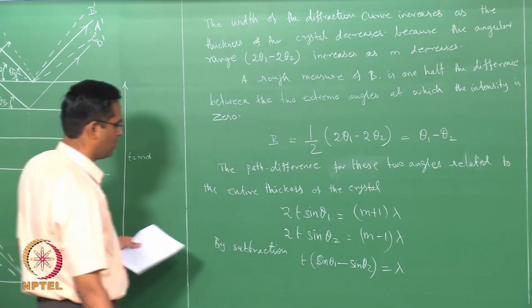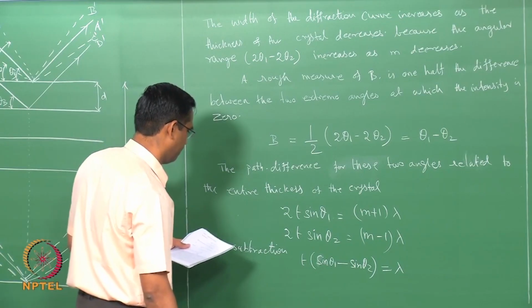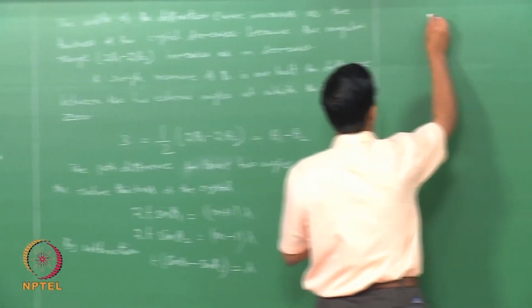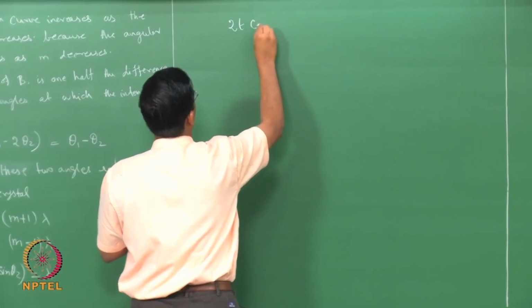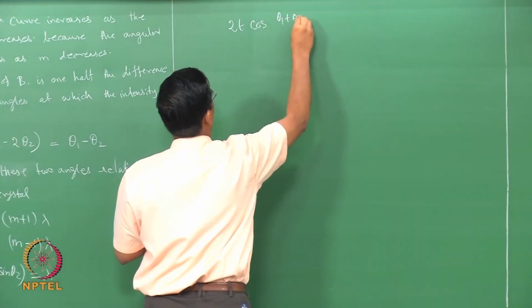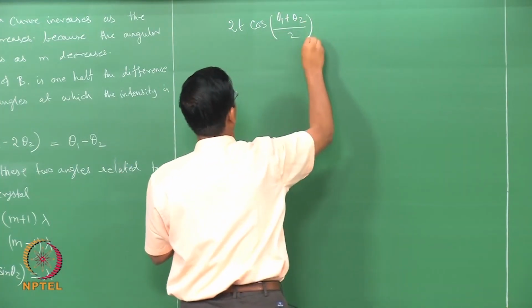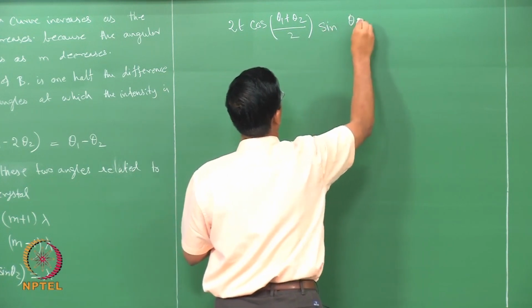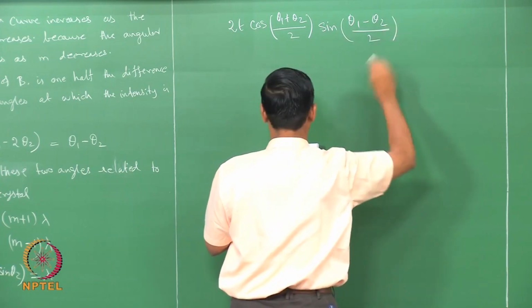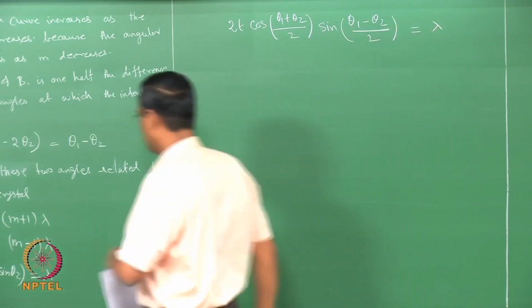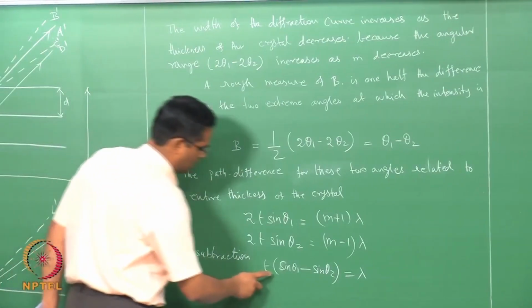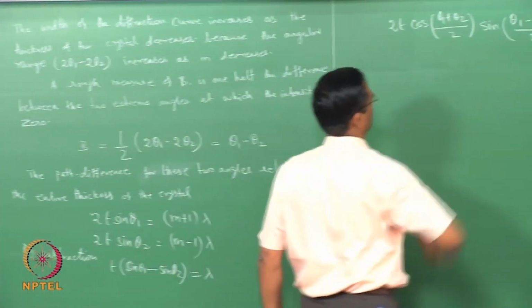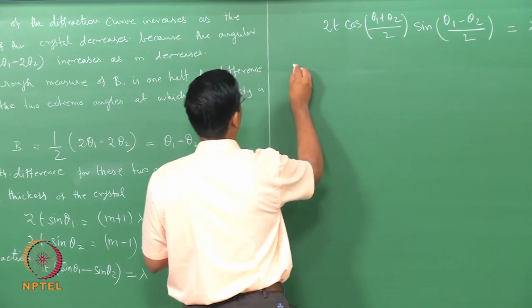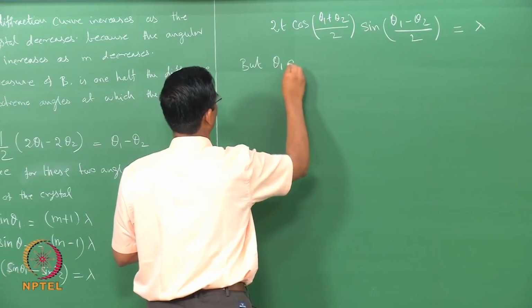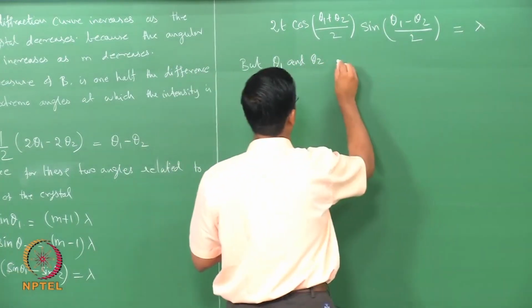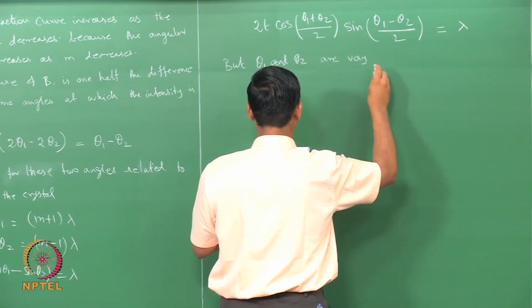So, we can use some trigonometric relations to replace this. We can write 2t cos of (theta 1 plus theta 2) by 2, times sin of (theta 1 minus theta 2) by 2, which is equal to lambda. What we have done is subtract these two equations and replace this with this trigonometric expression, and now we make some assumption: theta 1 and theta 2 are very nearly equal to theta b.